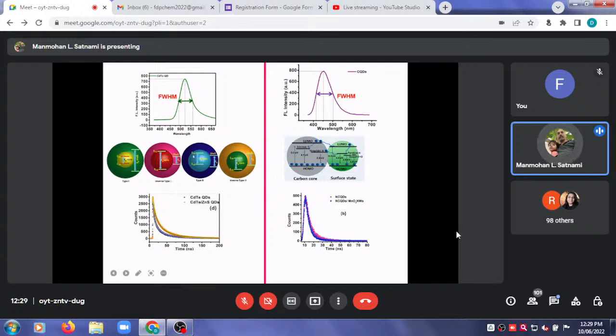So these are the band gaps of quantum dots. Actually, on the basis of the band gap, they give this emission. Okay, so here in the carbon quantum dots, the energy state arises between pi and pi antibonding. Later I will discuss. Okay, transition, and in between, if there is nitrogen doping in carbon quantum dot, then another energy states will arise. So what I am trying to tell you is that the fluorescence of carbon quantum dot is because of all these energy transitions. See, all the energy transitions, and the fluorescent emission of the semiconductor quantum dots are because of this energy transition, valence band to conduction band transition.